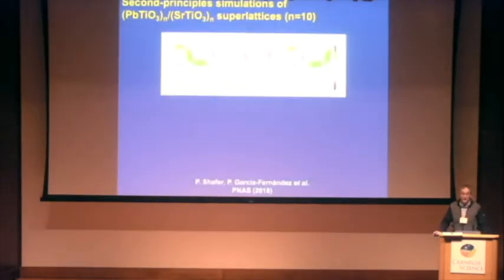So we have carried out second-principles simulations on lead titanate, strontium titanate, with 10 unit cells of each. And here you have some of the results we are getting. Here the arrows point the components of the polarization in the plane of the screen, and the colors are the component of the polarization perpendicular to the plane of the screen. So green pointing inwards, magenta pointing towards you.